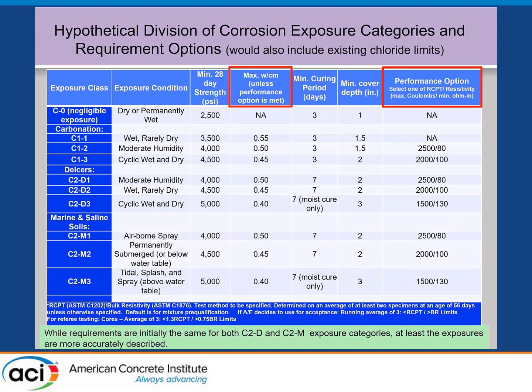One of the things we've been looking at, and this is part of the first straw man from the 321 Durability Code Committee, is let's fix these exposure classes, be a little more clear on what we mean. So C0 is no exposure, that matches. All the C1 exposures, no chloride, so we'll call those carbonation exposures. Better define them. And then we'll divide the chloride exposures, all the C2s, into de-icer exposures with various severities. And then marine exposures and saline soils will have maybe three there. We'll deal with the airborne spray, submerged, and tidal and splash zone, which tend to be the most severe. And let's up the requirements.